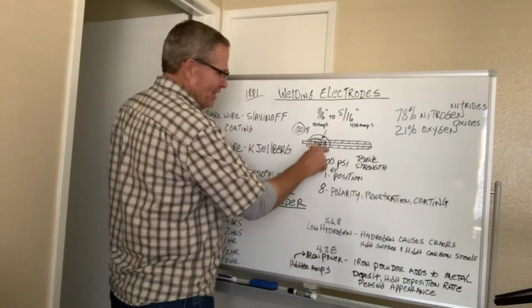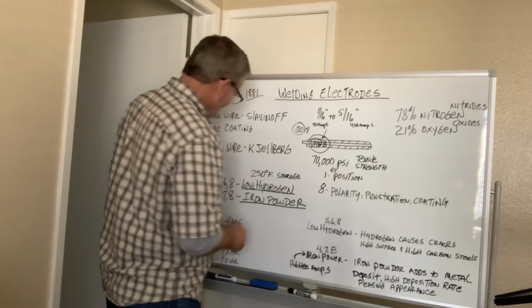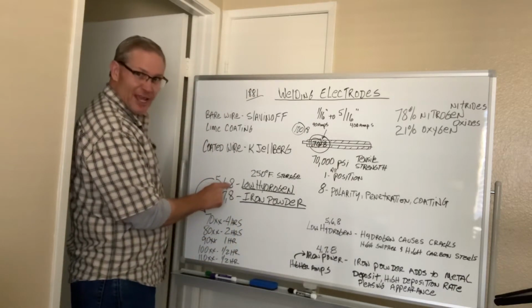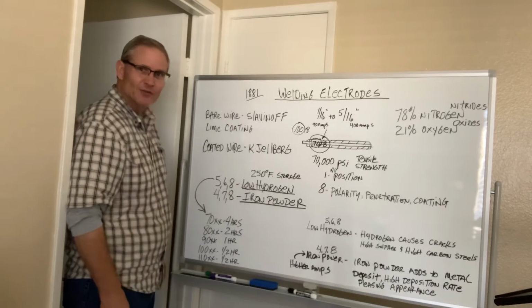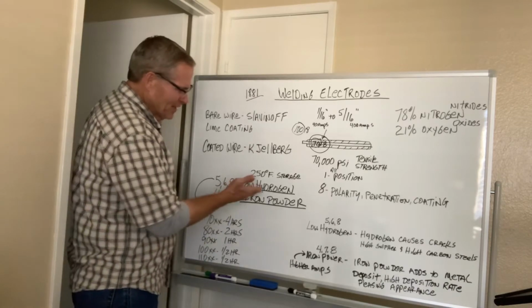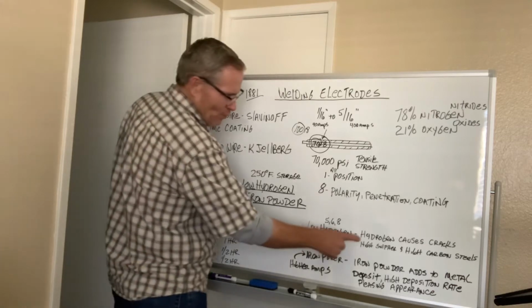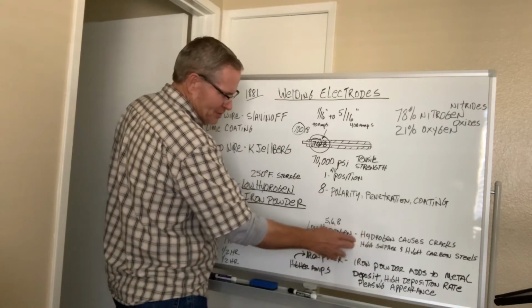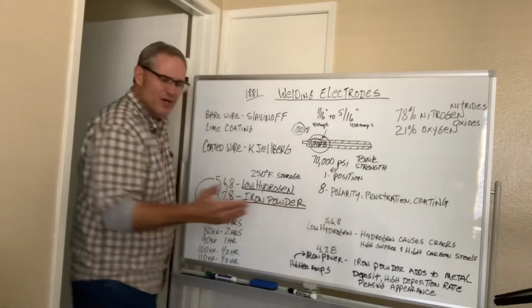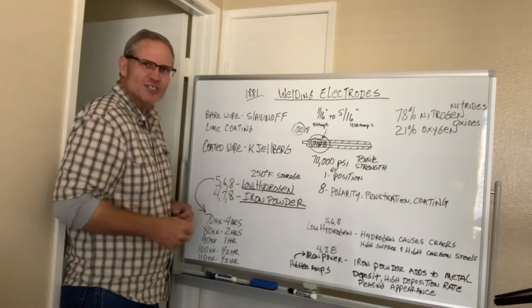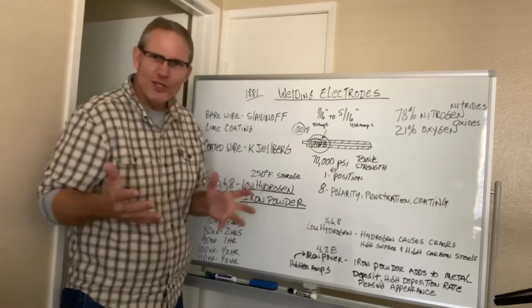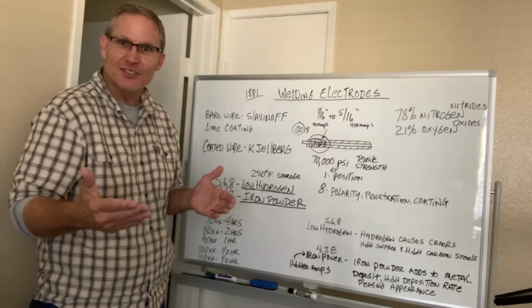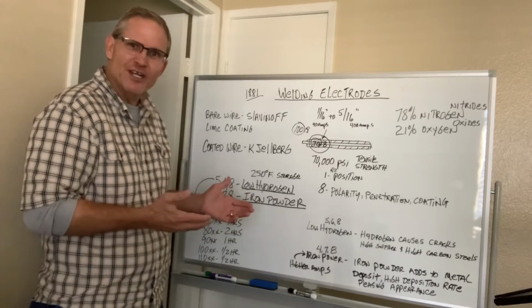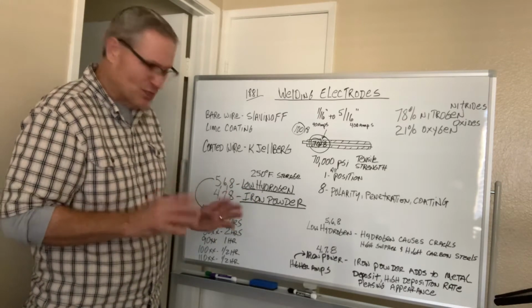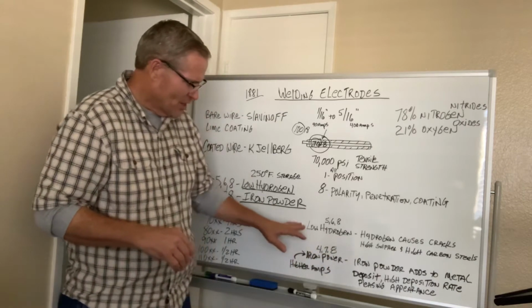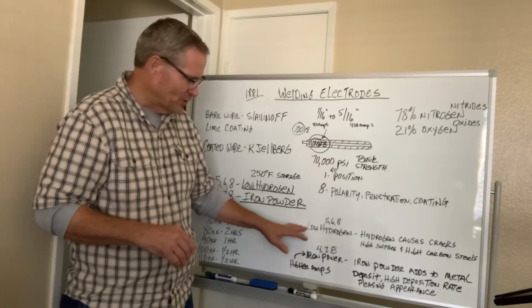This last digit right here, if it ends with a 5, a 6, or an 8, it's a low hydrogen electrode. Okay, we typically use low hydrogen electrodes when we're dealing with high sulfur and high carbon steels. What we know in the industry is that hydrogen causes cracks. And of course, moisture is H2O, hydrogen and oxygen. So we don't want hydrogen in the weld. And especially with high sulfur and high carbon steels, we go with low hydrogen electrodes.